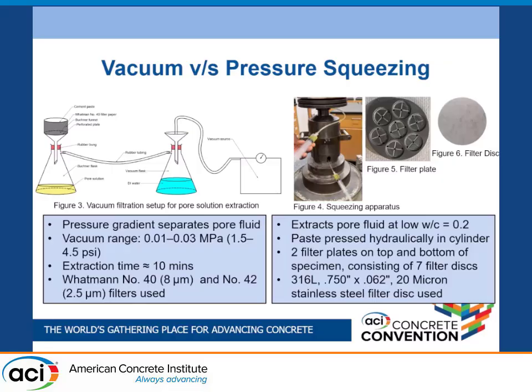For the squeezing apparatus, you can see in the right side figure, there is a large steel apparatus. It's very heavy, and for squeezing, we are extracting at a pore water cement ratio of 0.2. I already mentioned for comparison, we also extracted one sample at 0.4 water cement ratio, and the paste is pressed hydraulically in a cylinder.